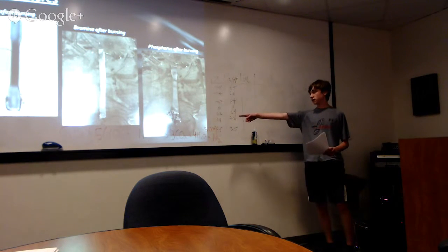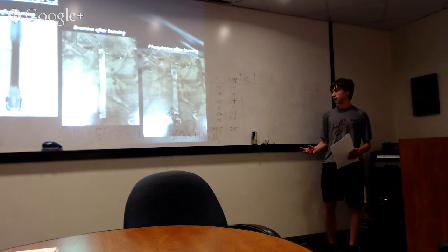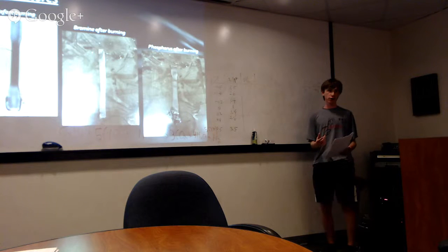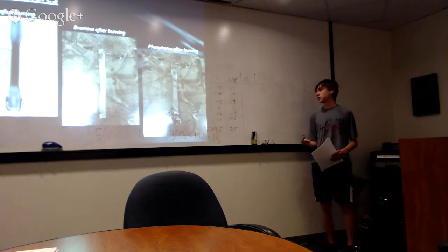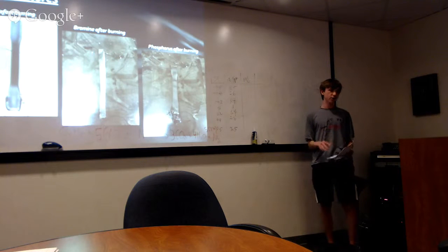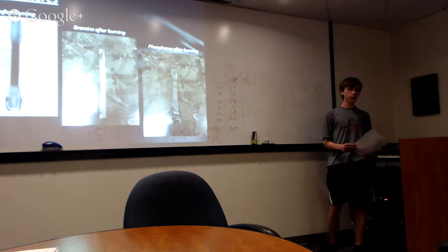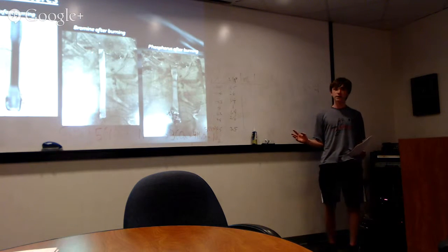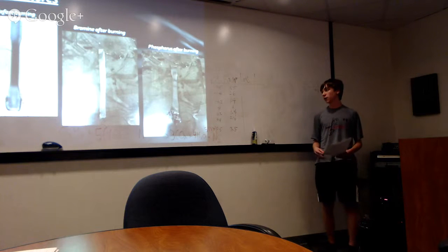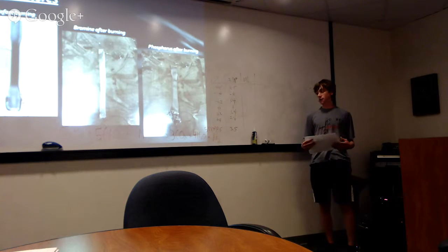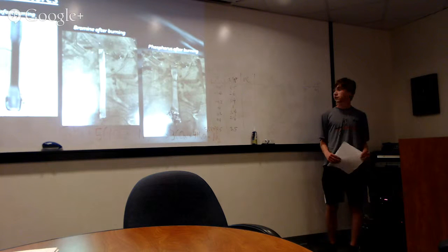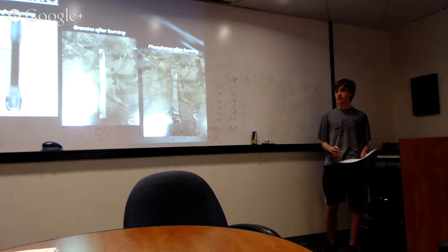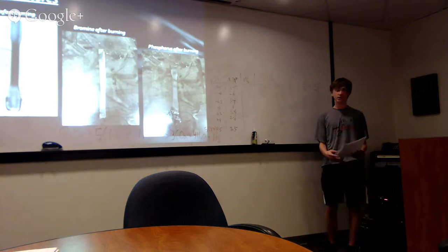On the right, the phosphorus on the bottom, it showed some burning and there were some plastic drips, but some of the samples worked. When there was a high concentration of phosphorus flame retardant in the plastic, it was more resistant to the fire. But when there were lower concentrations, it wasn't as resistant to the fire. And the bromine, it was basically the same damage done by the fire at lower concentrations and higher concentrations.